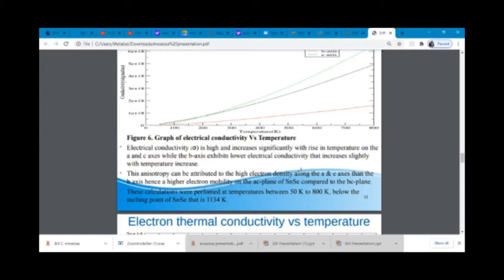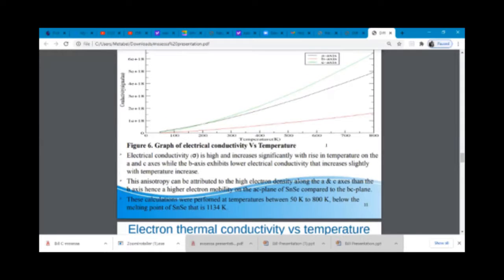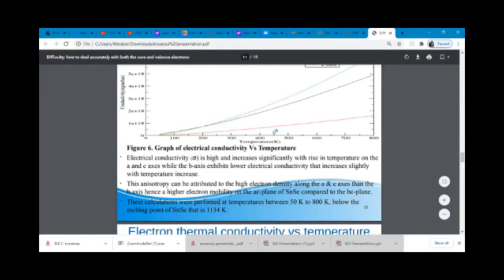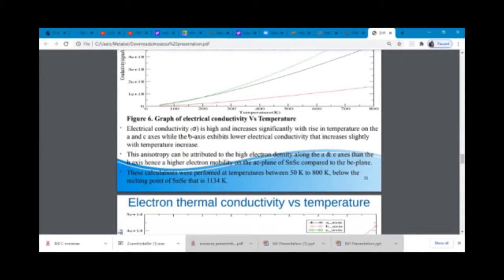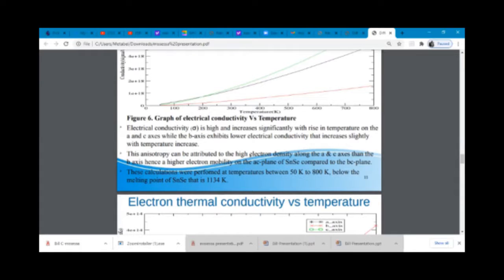And the increase was more pronounced on the A and the C axis, while the B axis exhibits very low electrical conductivity than the other 2 axes. And this anisotropy is attributed to the high electron mobility on the AC plane of the SnSe compared to the BC plane. It's also worth noting that these calculations were performed at temperatures between 50 K and 800 K, below the melting point of SnSe, that is 1134 K.